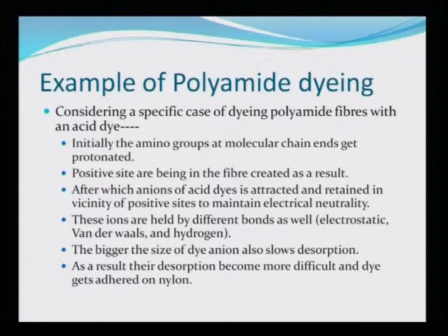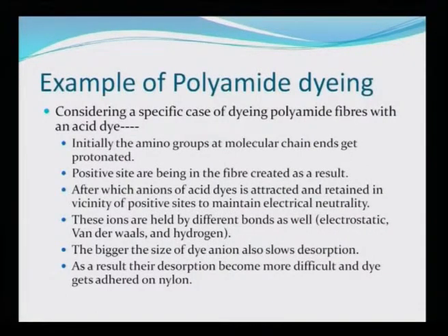These ions are held by different bonds, electrostatic, van der Waals and hydrogen bonding, all three of which are weak bonds. Nevertheless, if there are hundreds of these weak bonds, that itself will strengthen the hold. The bigger the size of the dye anion, the slower the desorption will be. As a result, desorption becomes more difficult and the dye gets adhered on nylon.